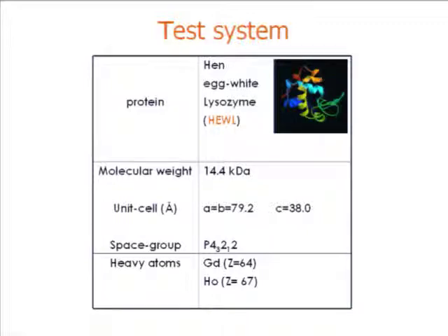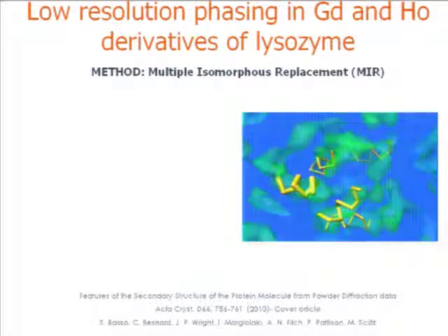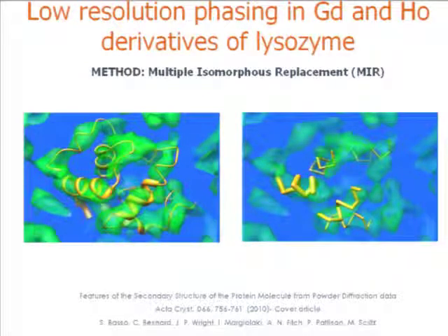So we had three samples in total, and from the differences in diffraction between the three, we could apply the isomorphous replacement method and find not only the shape of the molecule, but also the secondary structure of the molecule, which means basically the four helical regions of the molecule. This was the first time we saw secondary structure de novo, considering that there was no starting information about the structure. It was in collaboration with the group of Mark Schiltz in Lausanne.